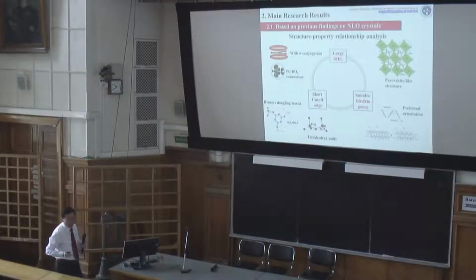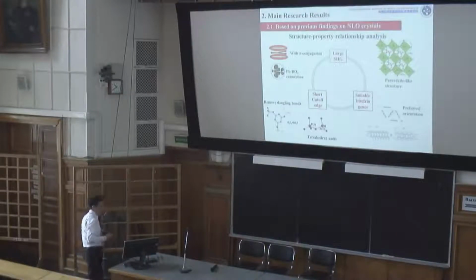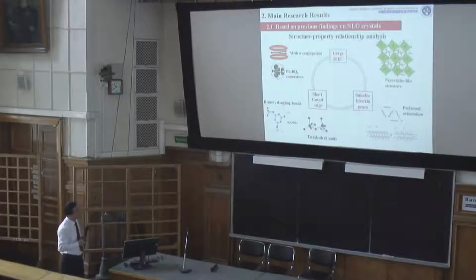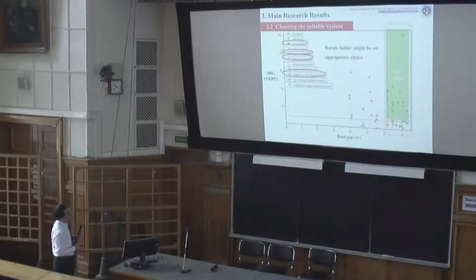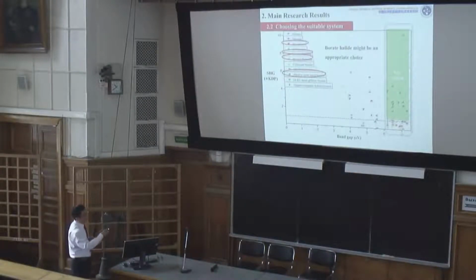This material is very interesting because this material has a perovskite structure. As we know, perovskite is a very famous structure. It can produce a large band gap. And also, it can produce suitable birefringence. So after our systematic research analysis, we found in this region, the materials can have a large band gap. It means its band gap is larger than 6 eV, and its SHG response is larger than 1 times that of KDP.